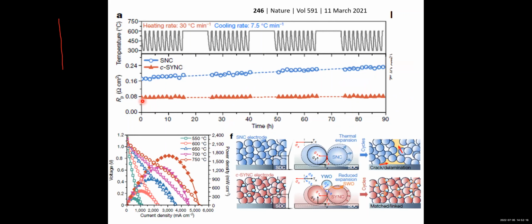This is because when we composite the two materials, we find some of the strontium atoms are exsolved from the bulk of the cobalt containing material, causing A site deficiency of the perovskite, which favors the oxygen conduction property and decreases the polarization resistance of the material.